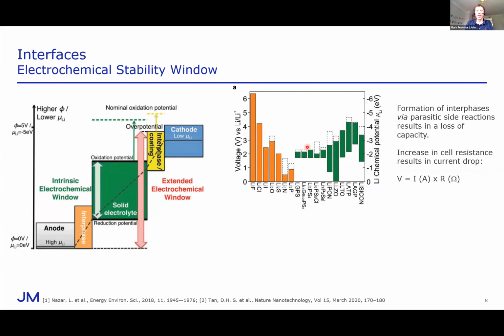And so on this chart on the right here, the green bars with the extended dotted lines correspond to the real electrochemical stability windows for a range of sulfides here, which are all quite narrow, and oxides, which are much wider stability windows, spread over a wide range of values of potential. And this just correlates with their chemical composition. Really, that's what it comes down to. So this is the main thing that holds back sulfides, which are very highly conductive, much more conductive than oxides, but their narrow windows are somewhat of a handicap.